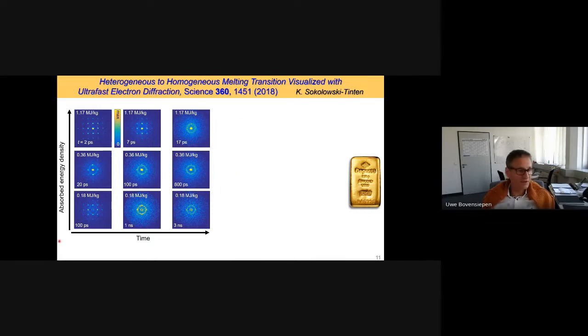And look here at these data. These are the transmitted diffraction images shown here as a function of increasing absorbed energy density, and here with increasing time. And if you look at these diffraction images, for example the one at the top left, you see a diffraction of a single crystalline material. But if you look at the other end, you find a diffraction image of a liquid. So Klaus has molten the gold with this laser excitation. But you can also see here images where you see a superposition of the crystalline and the liquid material. And this is what they were interested in.